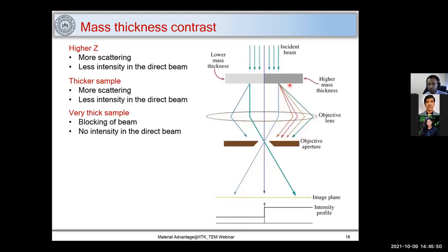Now based on this image, you can see that if I have a higher atomic number here, it will scatter more. If I have a lower atomic number, it will scatter less. So in the first case, we have higher Z, which is atomic number. So it causes more scattering, and there will be less intensity in the direct beam. And when you have a thicker sample, it also causes more scattering and results in less intensity in the direct beam. And if we have a very thick sample, it just blocks the beam and there will be no intensity in the direct beam.